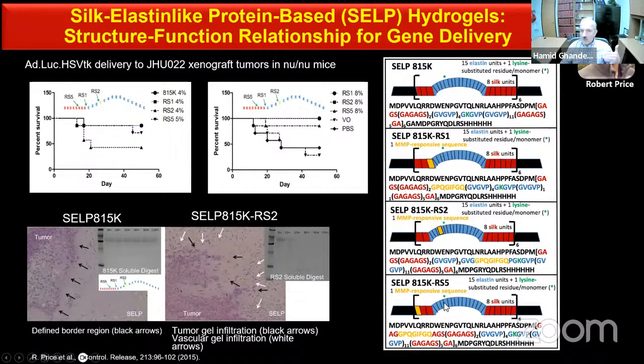So in this case, we did that, and then we mixed these polymers with the adenoviruses that I just mentioned, the therapeutic adenoviruses, intratumorally, and we looked at the percent survival of the animal. And what you're really seeing, bottom line, is that in one of these polymer cases, everything else being equal, meaning the concentration of the virus is equal, concentrations of the polymers, in this case, equal, we get survival up to 50 days, which is as long as we did these studies.